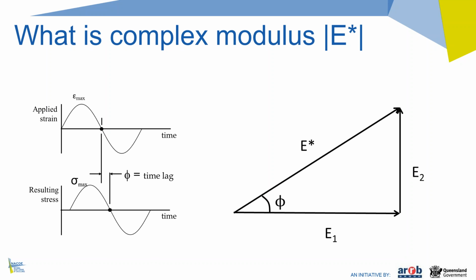behavior of the material. So we take into account the time lag between the maximum strain in the experiment and the maximum stress. The triangle on the right, I've tried to show that so we've got the maximum strain and the maximum stress, and the time lag is what we call the phase angle, shown in the figure on the right. E1 is the elastic component of the modulus, E2 is the viscous component of the modulus, and combined they represent the complex modulus.